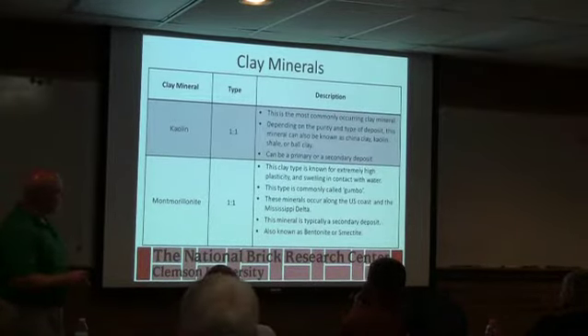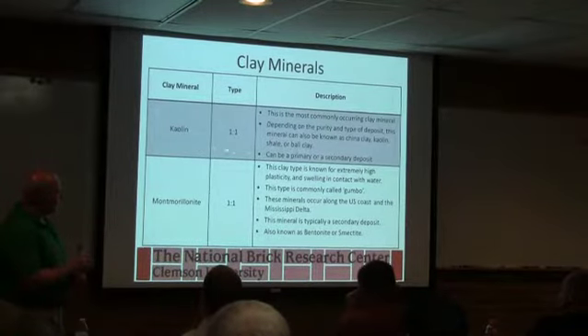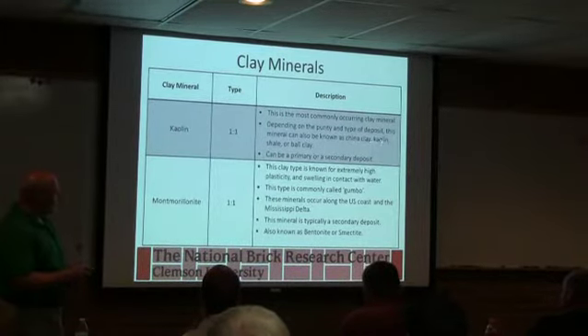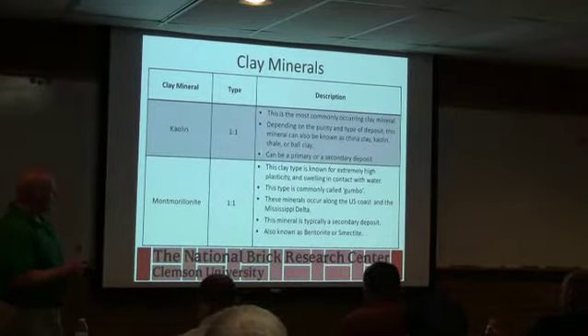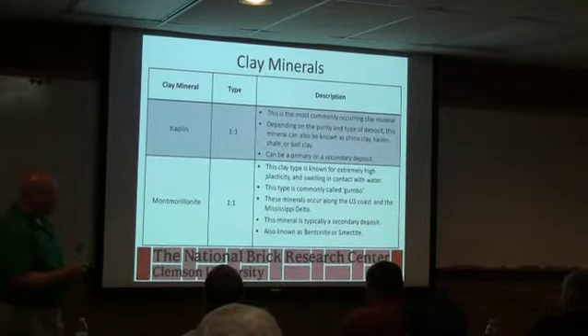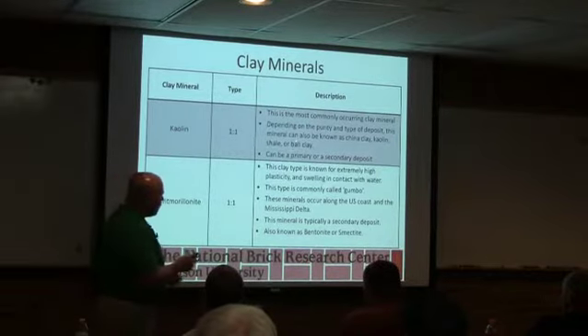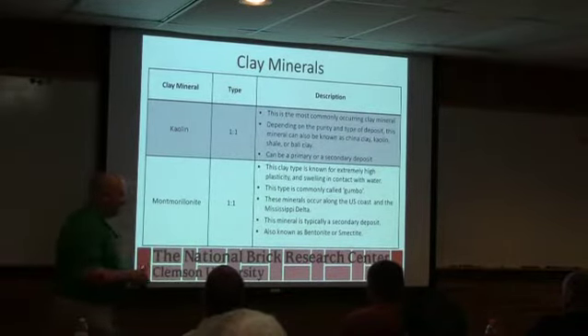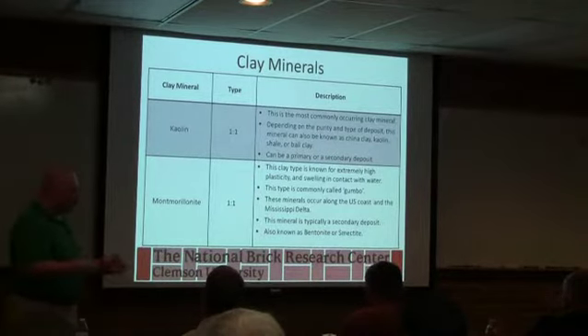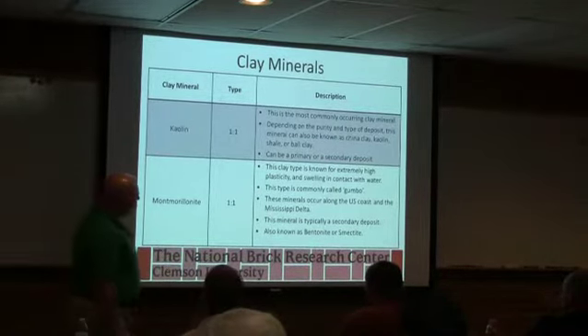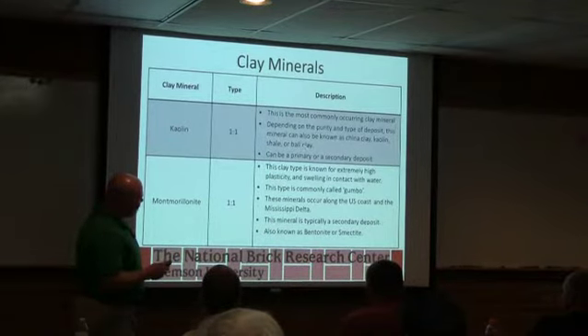So here are the clay minerals. Kaolin's the most common one, and it can be in anything from the really fine china clays, low iron content, kaolins that you might use to make tile or toilets or something like that. Shales, when you have a little more impurity, or they're also in ball clays you may use in your coatings. They call them ball clays because they used to go down in pits and they'd ball it up, make a big ball and roll it out of the clay. Because it was plastic enough they could do that. So they'd build up like a snowball and roll it out